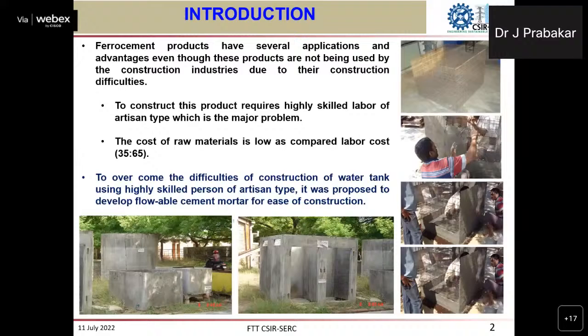Okay. If you see, since I said it is 25 mm thick, that is a 1 inch thick wall only. Therefore, we need a mason of artisan type to make this product in precise, uniform thickness. In those days, availability of manpower was not the issue, and the affordability of raw materials was the difficulty. Now it is the reverse. Now we can afford the material, but getting a mason of precise artisan type is somewhat difficult.